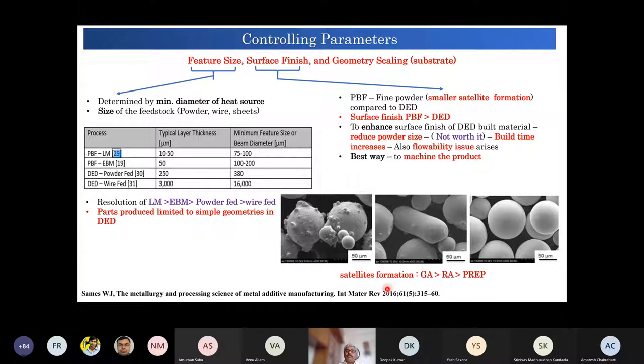So I was just telling about the satellite powders. This is the satellite. We have a powder, and on the surface of it we have small spheres. These create some problem in terms of packing. And this is another case, where the powder is produced in uneven shape. It's not very spherical. The powder which is spherical is considered the best for packing.